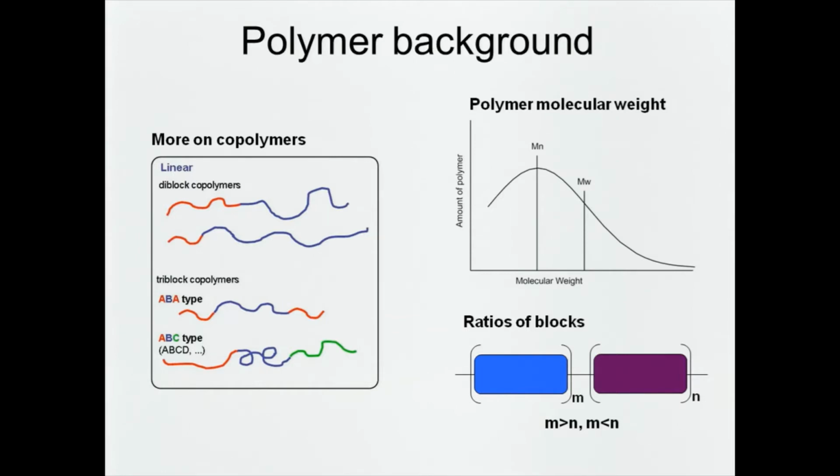And something to bear in mind if you're purchasing polymers or preparing polymers, the molecular weight will vary. There'll be a distribution. So it will say 1 million or 300,000 molecular weight, but that'll just be one of the parameters of the distribution. Then if you have different blocks, each block will have its own distribution also. So it gets a little bit complicated.